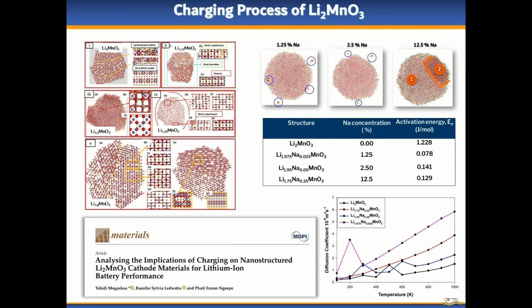So from that study, she was able to identify the optimal sodium concentration, which was 1.25%, and this yielded the lowest activation energy, meaning that this is the energy that is required for the lithium ion migration. And in turn, this works on the diffusion coefficient. So at that 1.25 concentration, we are able to obtain higher diffusion coefficients.